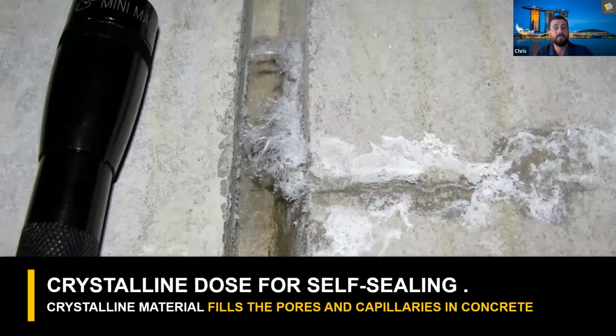So here's an example of crystalline self-sealing at work on a crack that's leading to a keyway. You can see the needle-shaped crystals clearly visible. So you will require an adequate concentration of crystalline in order to grow crystals that will self-seal the cracks that form. So when you increase the dosage, you increase the concrete's ability to self-seal consistently. So when specifiers attempt to save a small amount of money by going with a low dosage product, there's a major risk for leaks that are unable to self-seal. This leads to real-world issues such as corrosion.